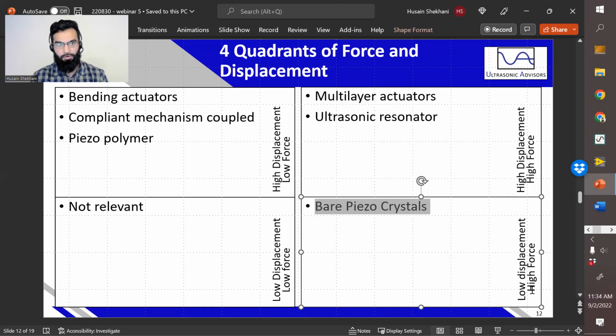If you were standing on that disc, you would go up by 0.4 microns, guaranteed. It would move you, but you couldn't tell that it's actually moving you. But if you do need low displacement and high force, you can even use a bare piezo crystal in different orientations. Now for high displacement, high force, we have a couple of options. We can use an ultrasonic resonator.